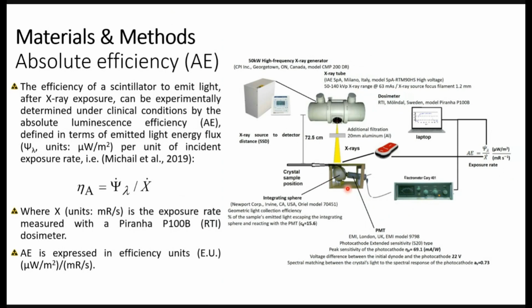And then the signal from the photomultiplier tube is fed to an electrometer. The signal then is digitized and transferred to a computer. So with this procedure, we have measured the produced voltages from the crystal upon irradiation. The voltage then is converted to the emitted light energy flux of the crystal.